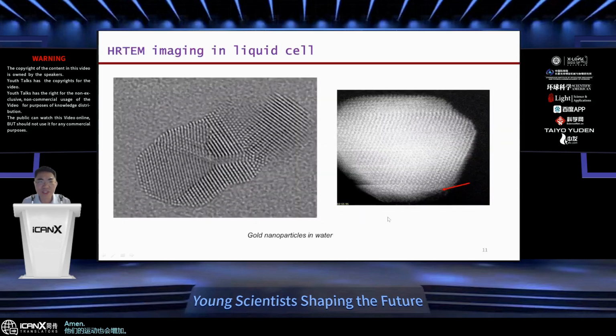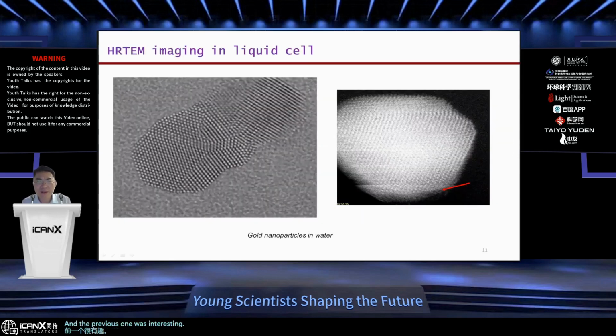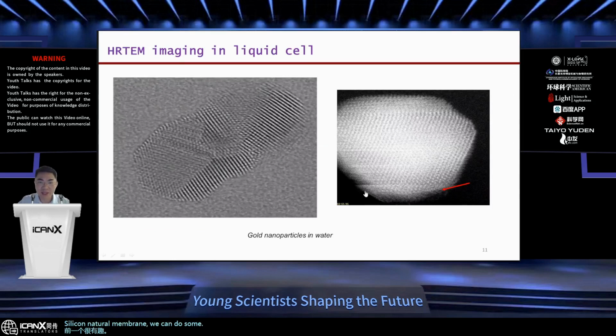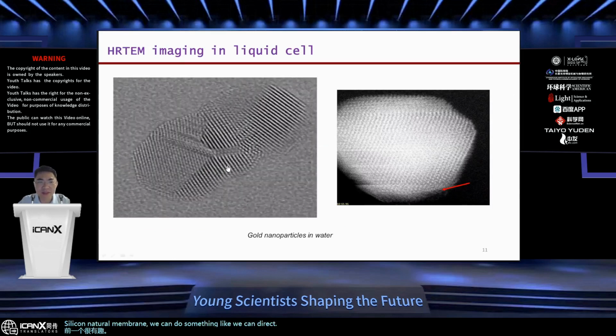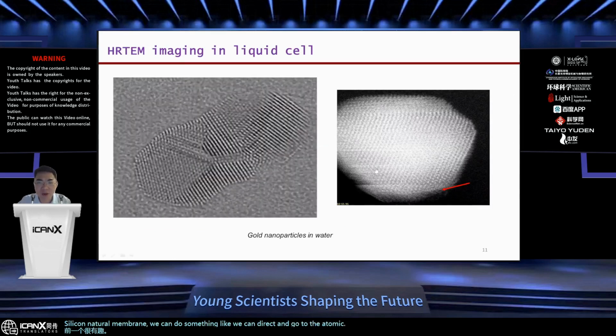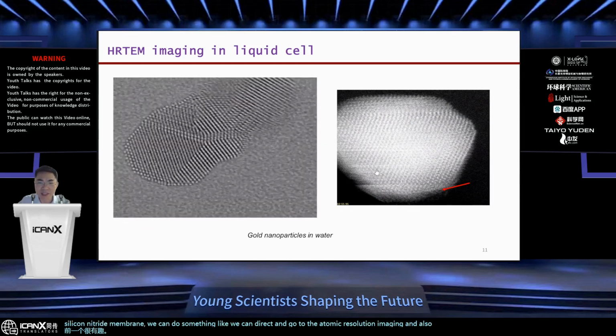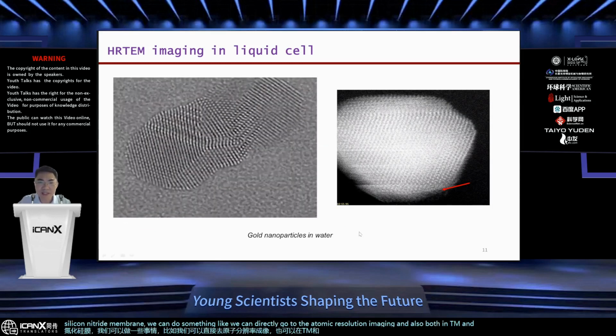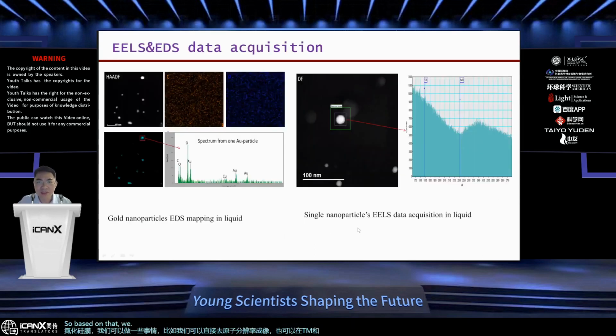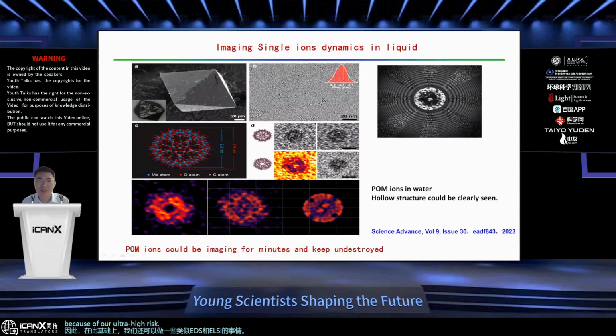And with an ultra thin silicon nitride membrane, we can go directly to atomic resolution imaging, in both TEM and STEM mode. Based on that, we can also do something like EDS and EELS in liquid. Because of the ultra high resolution, we can do something we could not before, like imaging of single ions and their dynamics in liquid.